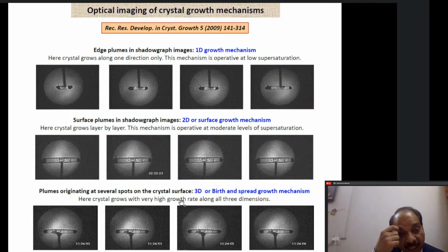And finally, we did another experiment in which we increased the supersaturation very fast. What happened in that case was that the plumes, which were initially visible only from the edges of the crystal, and in the second case from the entire surface, now in the third case we were able to see multiple sources of plumes on the top surface. This shows that the crystal is growing at several locations, and this was the case of the 3D growth mechanism, or in literature it has been referred to as the birth and spread type of growth mechanism. Here the crystal grows with very high growth rate along all three dimensions.